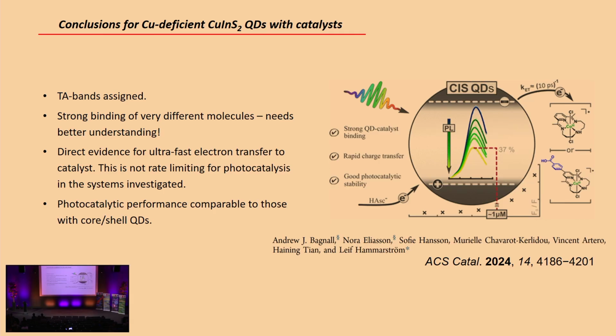We have direct evidence for ultrafast electron transfer to the catalyst, and this is not rate limiting for photocatalysis in these systems. And the photocatalytic performance was comparable to those that have a zinc sulfide shell to protect from charge recombination. So we can, of course, debate which one is better, but they were surprisingly good.